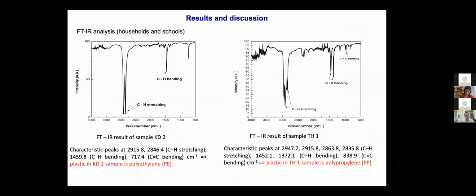Regarding the FTIR analysis, here are two examples where we found different functional groups: the CH stretching vibration and the CH bending vibration. Of course, we need a library to see the information and the different peaks for pure plastic or commercial plastic. We have not put it here yet, but we can conclude that the left-hand side is linked to PE, and the right-hand side is a PP.